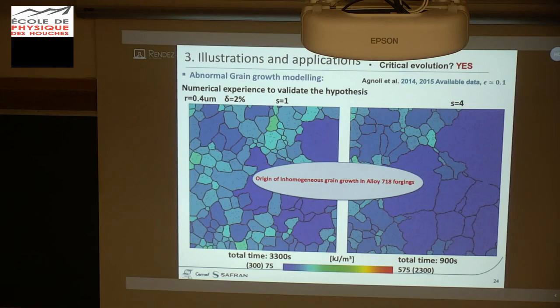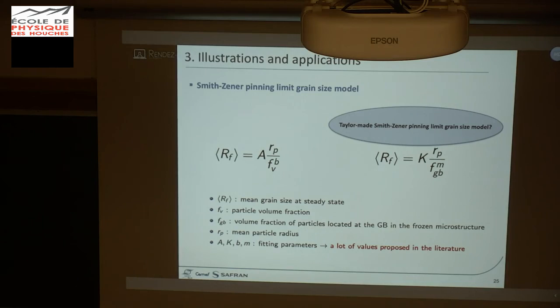And finally, this simulation was a way to validate and to improve the experimental procedure in the thermomechanical path for the forging of these alloys. So, another aspect, and I will stop here to have time for 5 minutes of discussion, is to use full field simulation to improve the classical mean field equation to predict limit grain size. I explained that a classical way to use Smith-Zener pressure is to predict the limit mean grain size of the polycrystal due to the presence of the second phase particles.